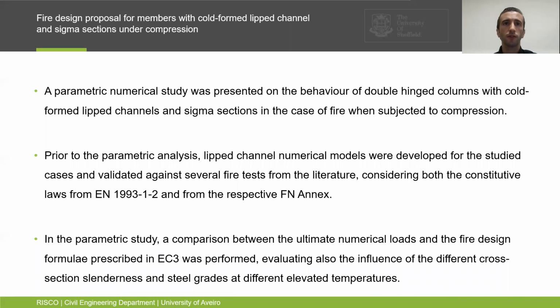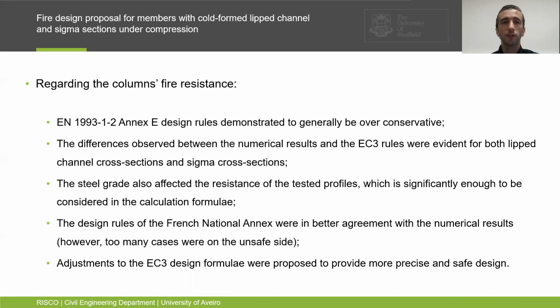To finish this presentation, the behavior of double-hinged columns with cold-formed lipped channel and sigma sections in the case of fire was presented with a parametric numerical study. Lipped channel numerical models were developed for the studied cases and validated against several fire tests from the literature. A comparison between the ultimate numerical loads and the fire design formulae prescribed in Eurocode 3 was performed. Regarding the columns' fire resistance, the current design rules demonstrated to be generally over-conservative. The steel grade affected the resistance of the tested profiles significantly enough to be considered in the calculation formulae. The design rules of the French National Annex were in better agreement with the numerical results.